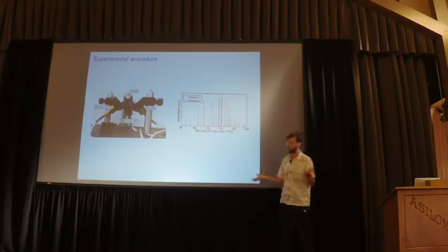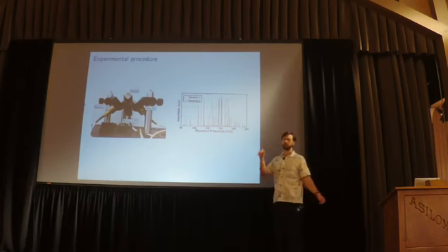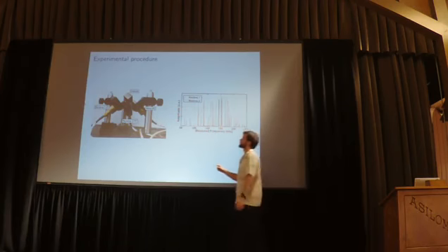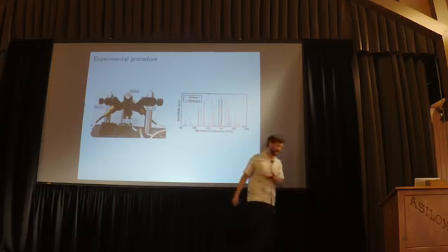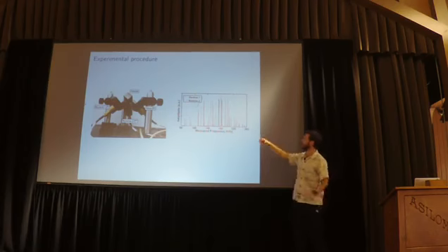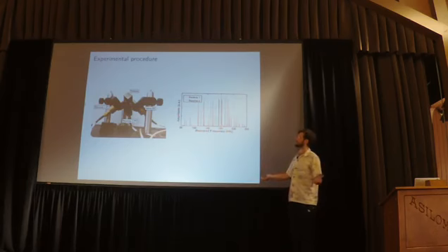And much in the same way that we can ring a gong, we can take a little lump of material, one of these superalloy materials, put it in some sort of ringing apparatus, and figure out where it likes to vibrate, the frequencies, the noise that it makes.